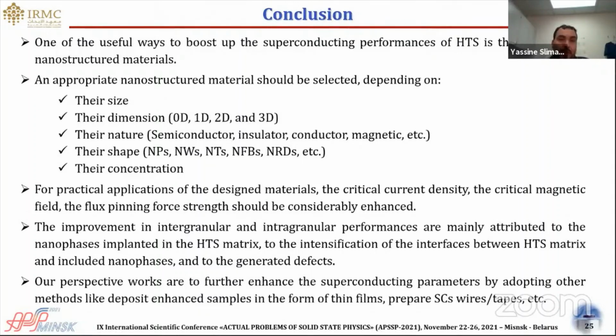In addition, the inclusion of nanostructural materials could generate structural defects that could reinforce the pinning strength of vortices. Of course, one of our perspective works nowadays is to further enhance the superconducting parameters by adopting other methods, like deposited enhanced samples in the form of thin films, and also preparing superconducting wires and cables for energy transportation.